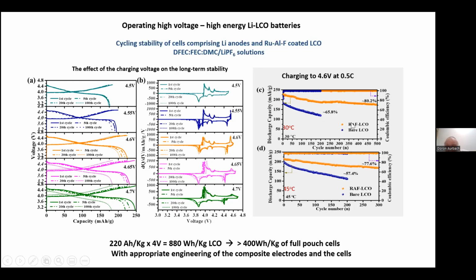And here you can see different types of coating. Here we have another type of coating. I don't expose it at the moment, but we see very nicely that even at 20 degrees and 45 degrees C, compared to untreated material using our favorite electrolyte solution, we have very impressive stabilization starting from 225 milliampere hour per gram, which is not too bad.